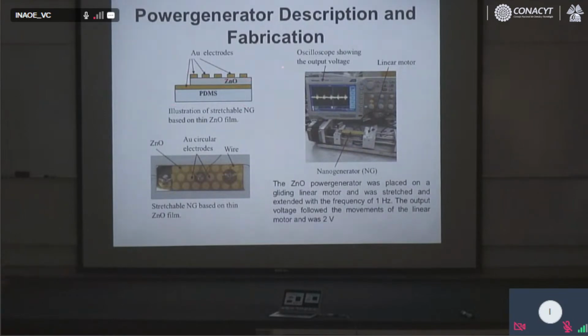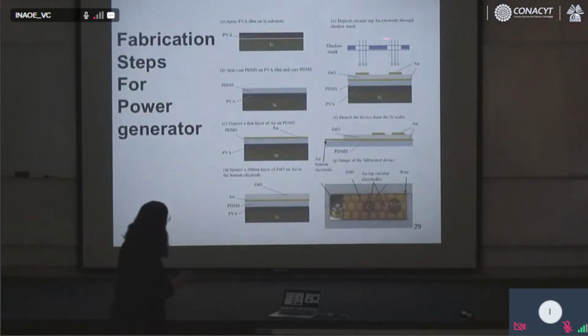So zinc oxide, in order to be transformed into a power generator, in order to collect the voltage, needs two electrodes, one electrode on top and one on the bottom. So you have PDMS, you fabricate gold. We have a layer of gold here, constant. We don't require a mask for this gold. Then we sputter zinc oxide, and then we fabricate the electrodes on top with the shadow mask. We just did the shadow mask, and we sputter gold, and then we need to detach the whole device.